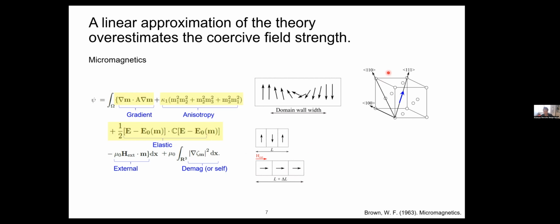And you'll see some of these constants have either 100 or 111 in the subscript. What that means is the amount of strain that you generate when the material stretches along a specific crystallographic direction. So there's some elastic energy associated when your magnetization is being switched from one direction to the other. And this term, in fact, is often not included in several calculations because magnetostriction constants are quite small. They're measured on the order of microstrains, that's like 10⁻⁶. So they're not suspected, and rightly not suspected, to play a major role here.